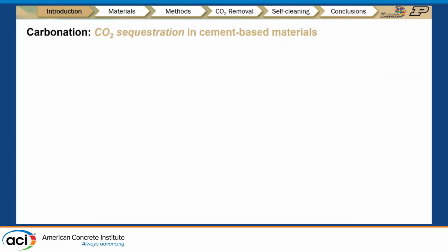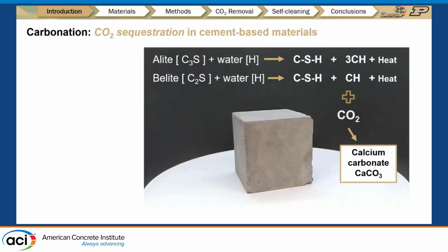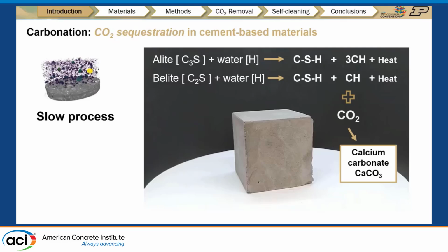So we know that the carbon dioxide sequestration in the cement-based material is called carbonation. It's mainly the cement hydration products reacting with the carbon dioxide in the ambient air and forming calcium carbonates, and this calcium carbonate will stay inside the cementitious material. However, this is going to be a slow process. It's going to take decades to complete. Besides, it was also estimated that around 40% of the carbon dioxide we produced has been reabsorbed through this carbonation process.